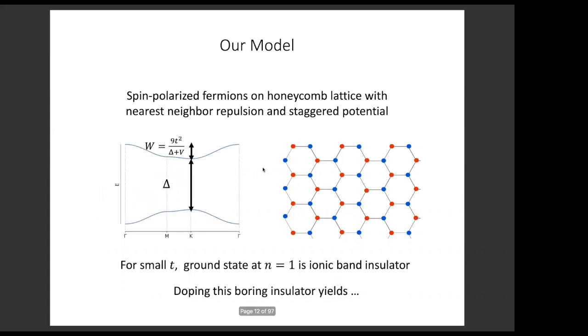Yeah, sorry. Okay, so in this very simple model, let's first consider the case of a filling of one electron per unit cell. In this case, the ground state is an insulator. This insulator is adiabatically connected to the atomic limit. If the hopping t is turned off, then it's clear that at this filling of one electron per unit cell, all electrons want to be in the A sublattice because the B site has a higher energy delta. It's also adiabatically connected to the non-interacting limit when V, the nearest neighbor repulsion, is turned to 0.